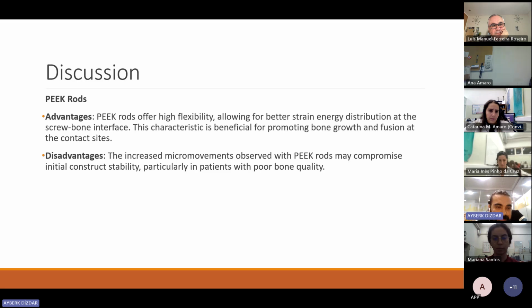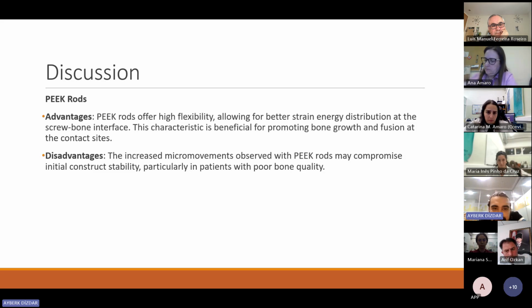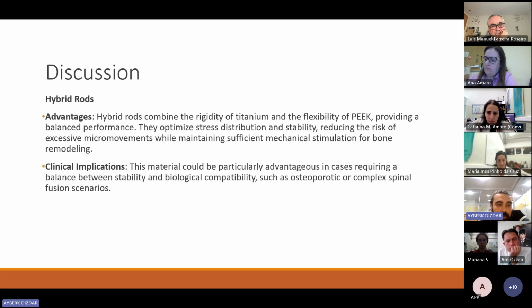PEEK advantage: PEEK rods offer high flexibility, allowing for better strain energy distribution at the screw-bone interface. This characteristic is beneficial, promoting bone growth and fusion at the contact sites. The increased micromovements observed with PEEK rods may compromise initial construct stability, particularly in patients with poor bone quality.